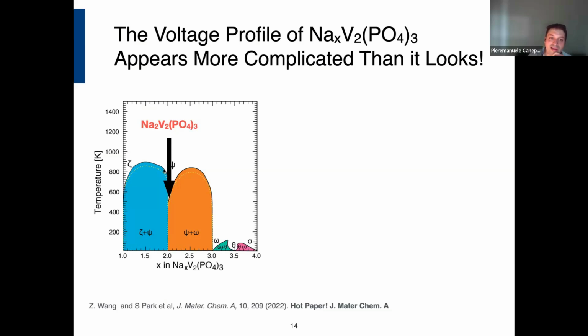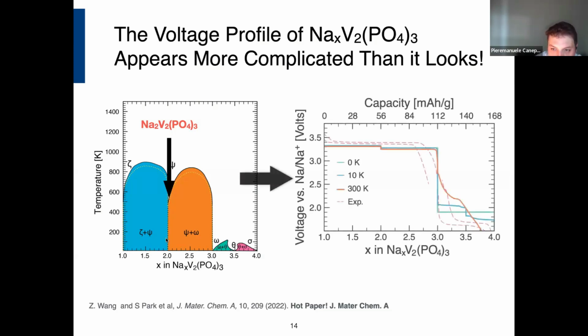However, the phase diagram here reveals that at x equal 2, meaning 2 sodium per formula unit, there is a new single phase. So you have a line compound here, and this line compound was never reported experimentally. Of course, when you see such a thing, you start believing the theory is wrong, as usual, but maybe this time I will demonstrate that the theory has something positive to say.